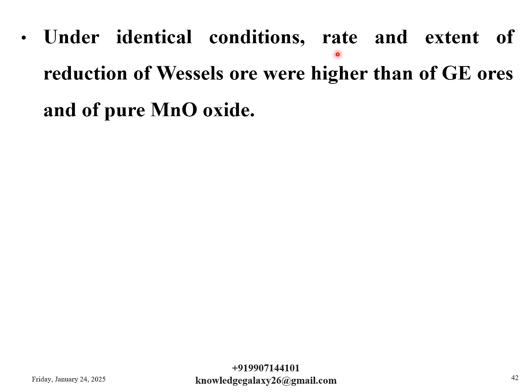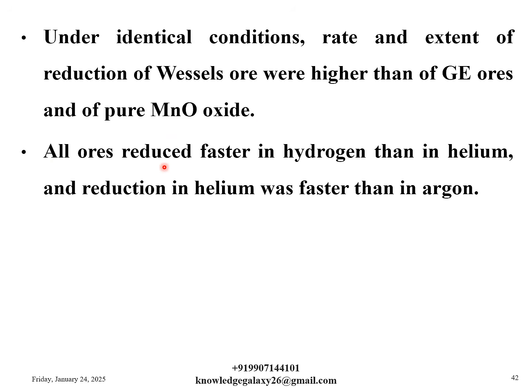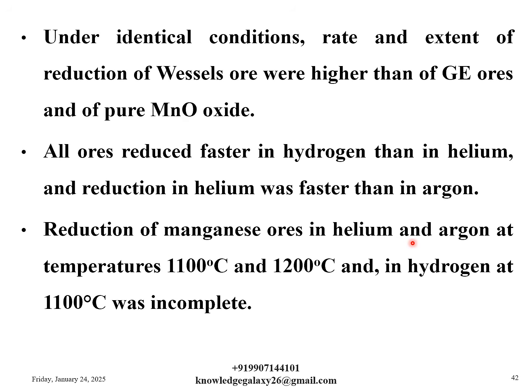Under identical conditions, rate and extent of reduction of Wessel's ore were higher than of GE ores and of pure MnO. All ores reduced faster in hydrogen than in helium, and reduction in helium was faster than in argon. Reduction of manganese ores in helium and argon at temperatures 1100 degrees Celsius and 1200 degrees Celsius and in hydrogen at 1100 degrees Celsius was incomplete.